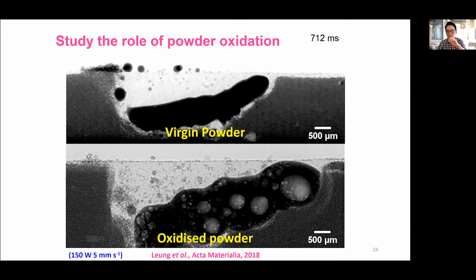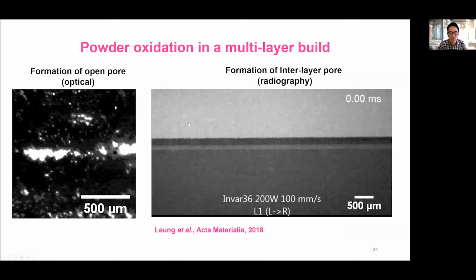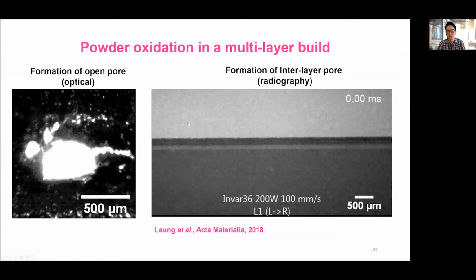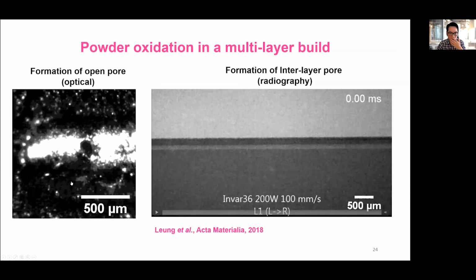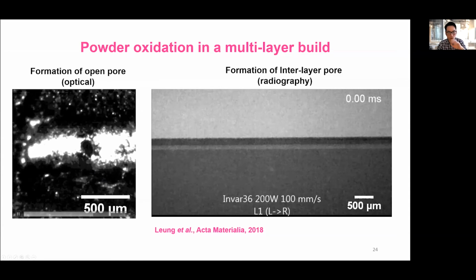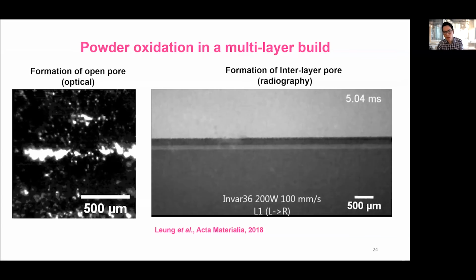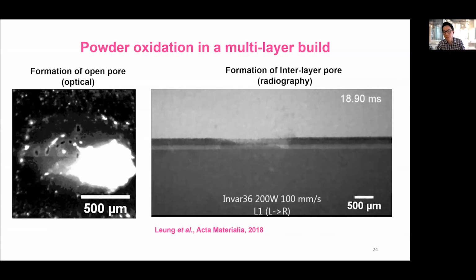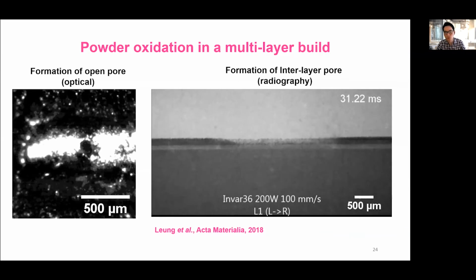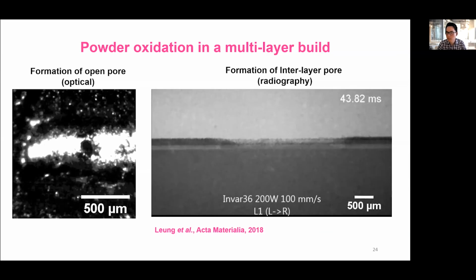So what you can see here, the powder is actually on the right hand side, where my cursor is. The middle, the black really dark bit, is the melt track. So there are many other things you can see using other types of imaging. The black dot that appears on the left-hand side is an optical image. Now you're looking at the surface of the powder bed, but we don't actually know what's happening underneath, right? Which is why we needed to use the X-ray imaging technique.